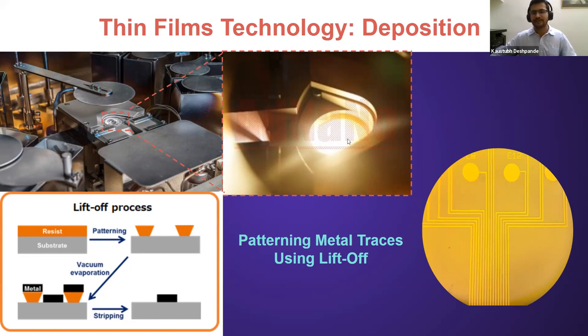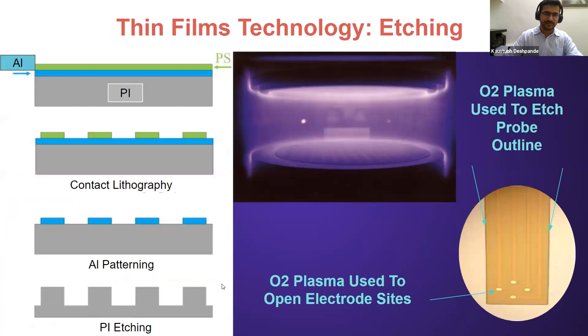At this stage, you have an electron beam that gets shone onto a metal crucible, a tungsten crucible with metal pellets in it. And the heat from the e-beam is able to not just melt the metal pellets, but also evaporate it. This evaporated metal then condenses onto the wafer. And that's how we pattern metal traces down. So we do this with titanium, gold, and platinum. And then eventually, once the deposition is done, we strip off the resist and just have the metal remaining in the areas where we want it to be.